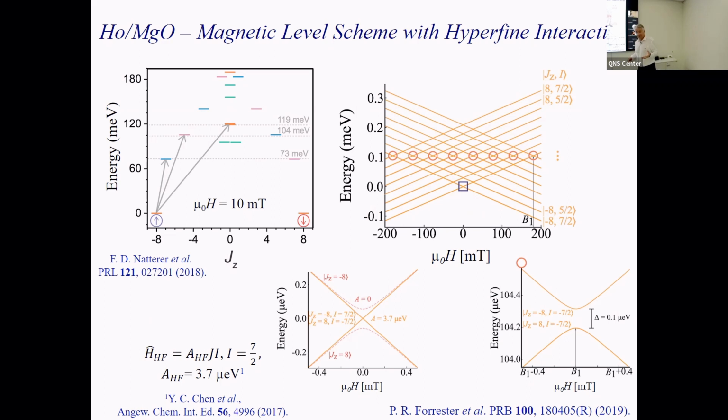Now, how can we explain that this holmium is nevertheless a stable state? You can either say you just need a magnetic field to make it stable, or something else happens. There are two ways to explain it. One is that you take into account the polarization of the external shells again, and they couple strongly to this total angular momentum. This means that the ground state is not ±8, the ground state is ±8.2 or 8.1 or something. And a good quantum number is not the J that comes from the 4f electrons only, but the total angular momentum composed of the two different levels, the external shells and internal shells.